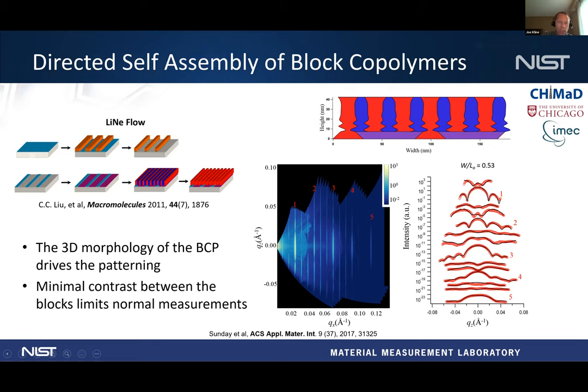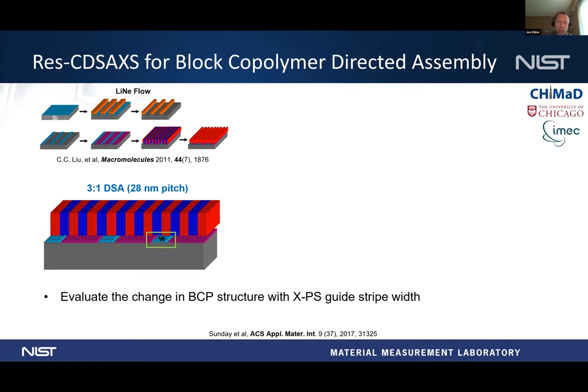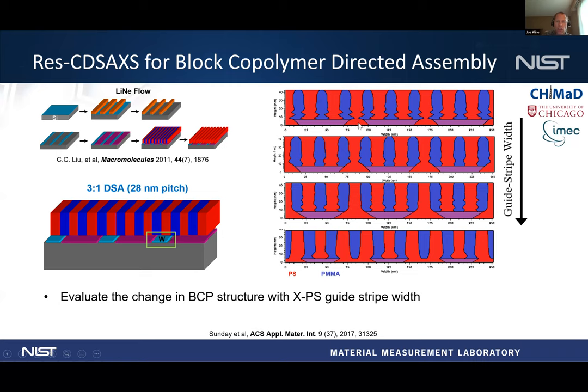And so working with the Neely group, they fabricated a series of different samples for us where they varied the width of this guide stripe here at the bottom. And then we applied the CD-SAXS method to it. You can see as the red part here, which is this guide stripe, gets bigger, the fluctuations go down a little bit. Particularly, I think the fluctuations here are big because this guide stripe is smaller than what the polystyrene is, so it's not really happy. And once that gets a little wider, it gets a little happier and can spread out. And then when you get bigger, it starts to not get happy.